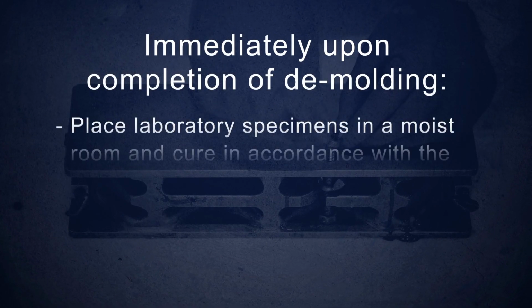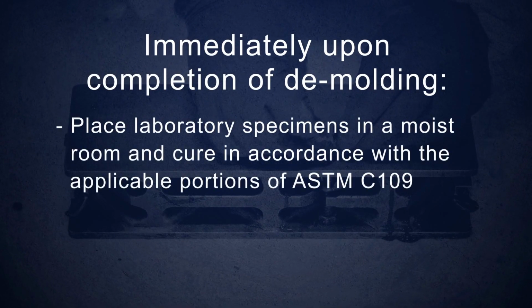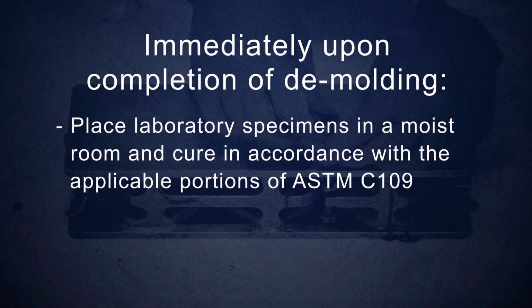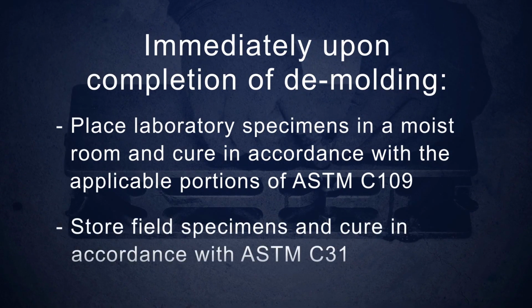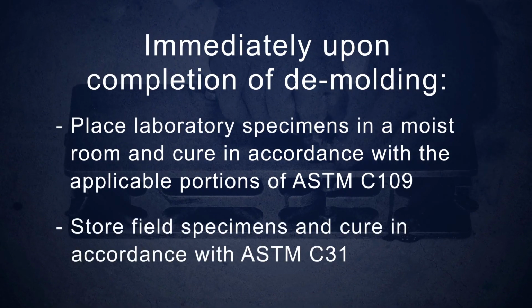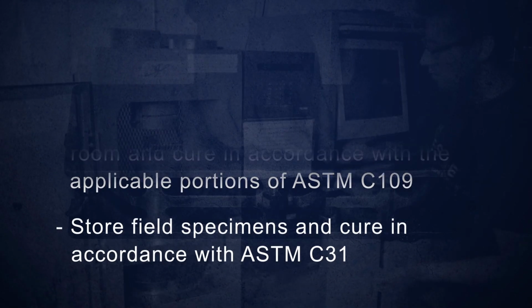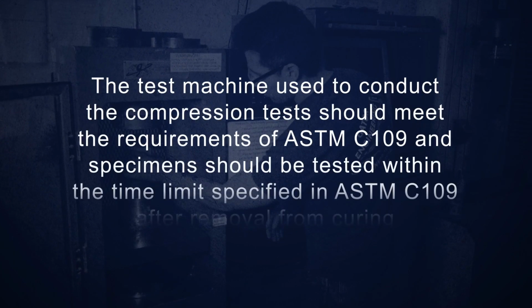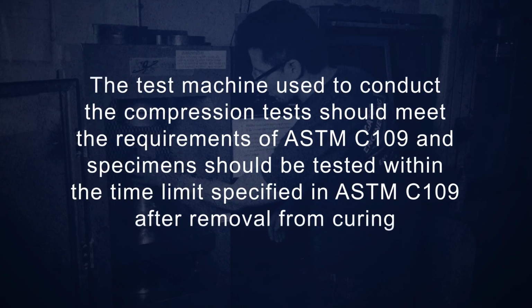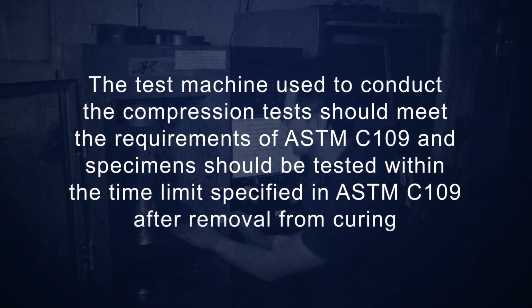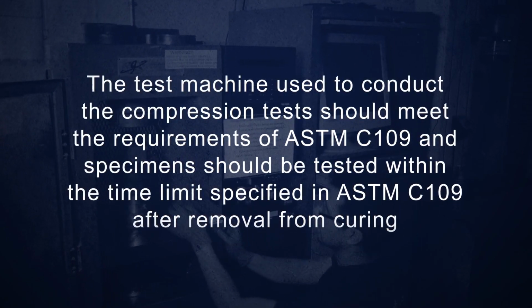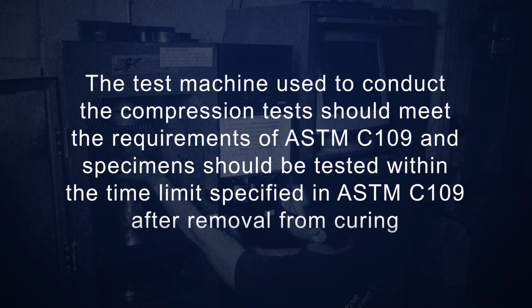Immediately upon completion of demolding, place laboratory specimens in a moist room and cure in accordance with the applicable portions of ASTM C109. Store field specimens and cure in accordance with ASTM C31. The test machine used to conduct the compression test should meet the requirements of ASTM C109, and specimens should be tested within the time limit specified in ASTM C109 after removal from curing.